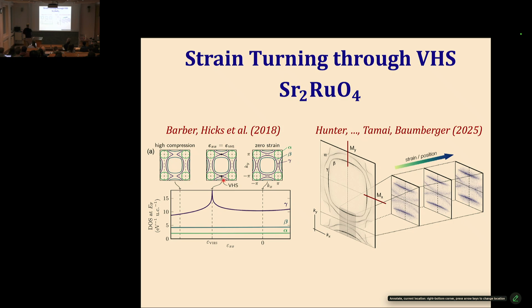When you apply uniaxial strain, the Fermi surface deforms. This is what it looks like at zero strain. And as you apply strain, one of the three Fermi sheets in the system, called the gamma band, is deforming most strongly. This piece of the Fermi surface is approaching the Brillouin zone edge, touching its mirror image from the other side, and reconnecting in this way. So the idea is, if you look at the density of states of this gamma Fermi sheet, it's undergoing a Van Hove singularity.